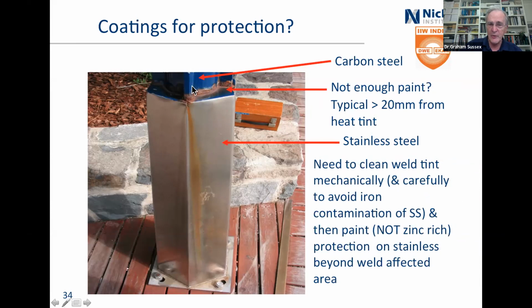You need to make sure you've cleaned the heat tint off and cleaned off all the muck from the weld, and do it mechanically, preferably, because if you do it chemically, you wind up etching the carbon steel as well. And then you paint it, but you do not, under any circumstance, use an active paint. You don't go using zinc rich, because you put that onto the stainless steel, and if there's any defects in the coating, this, mind you, zinc rich would be a primer, of course. If you do that, then you wind up with all sorts of corrosion between the zinc, which is right up one end of the galvanic series, and the stainless steel, which is halfway up.